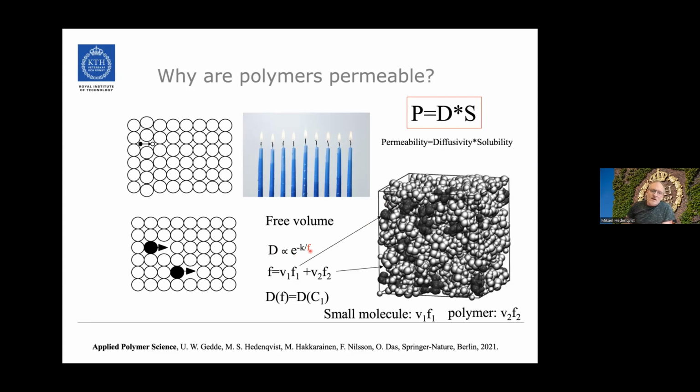material. And for polymers without strong interactions, without hydrogen bonding and so on, one can actually add the free volume from the polymer and the diffusing molecule. So the diffusing molecule has a free volume F1 here, and the polymer has a free volume F2. And you can actually add up these and get the total free volume in the system.